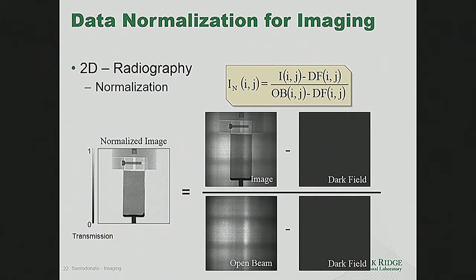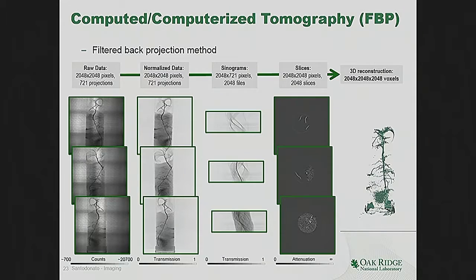As far as how often, you really wouldn't want to present an image like that usually. You always want a normalized image. So the typical experiment, at some point each day you collect some open beams and then you collect all these raw images. The process of doing this is automated through the analysis software. And I think the next slide, did I mention? Well, it's coming up.